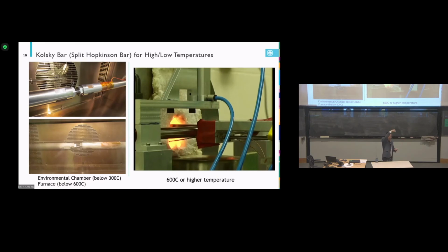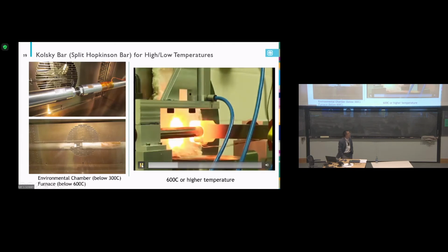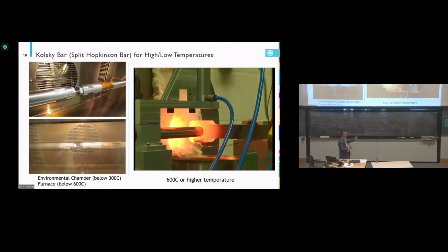We use a third actuator to punch the specimen out and it drops into the water. So you can see that's here, that's water. There's water here. Now here, this is not a high-speed camera. This is a regular camera. You can see how fast it is. It's done. Dynamic compression is done. Then you can see the punch drops the sample into the water for the quenching process.